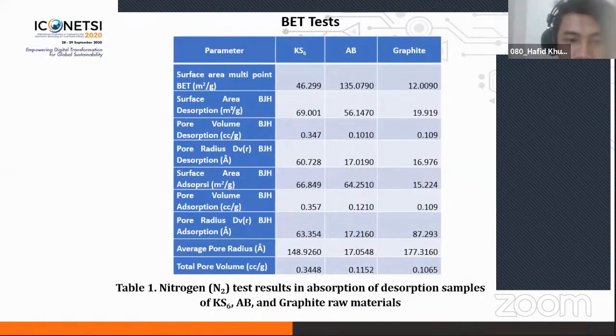This is the BET test. The specific surface area of the sample was calculated using BET. From the BET test result, AB material has a larger surface area than KS6, which is 135.8 square meters per gram.